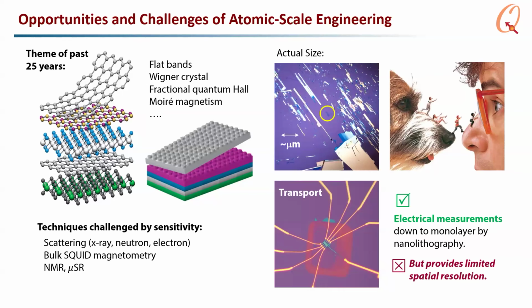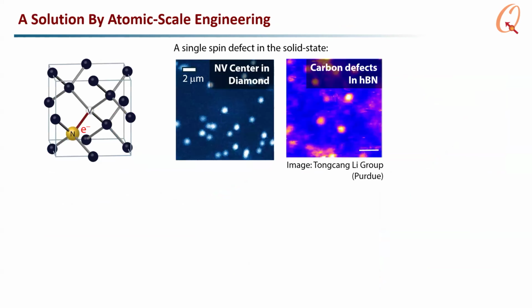On the other hand, there's a whole host of other techniques, such as scattering-based techniques, where you're challenged by sensitivity quite a bit. So neutron scattering, Lorentz transmission electron microscopy, where you're relying on the interaction of the beam through a thickness of the sample, cannot really access the same van der Waals materials. And you see some of these other probes are some of our best probes for bulk magnetism. So these are two challenges that can conveniently be addressed by other advances in atomic scale engineering, most notably